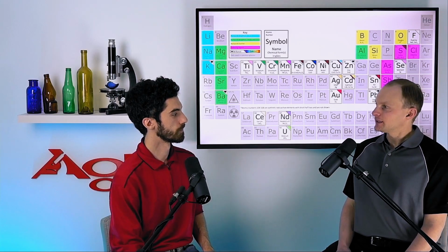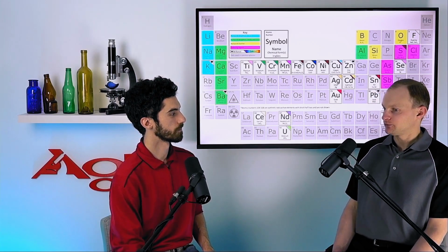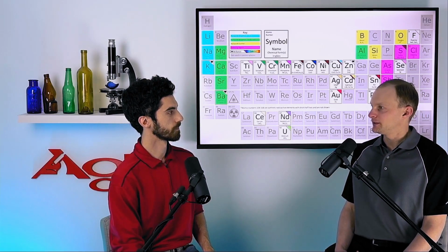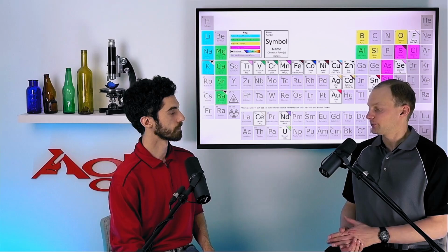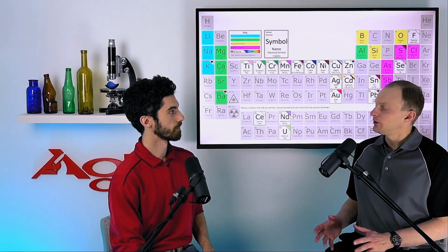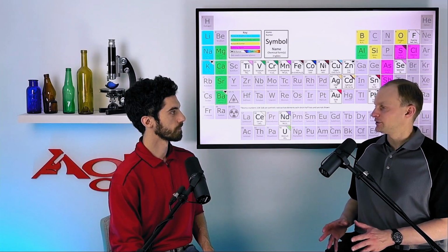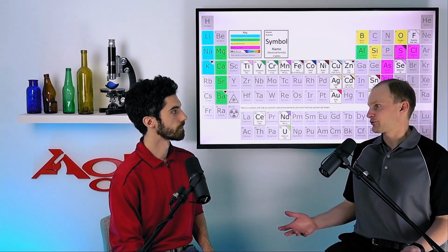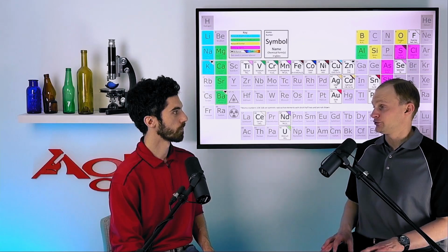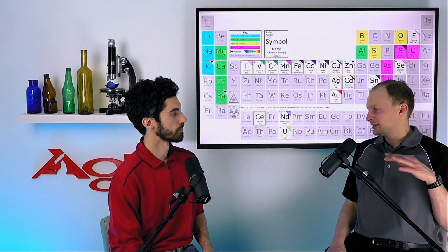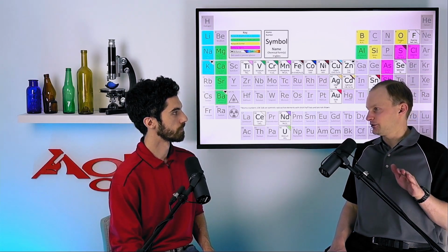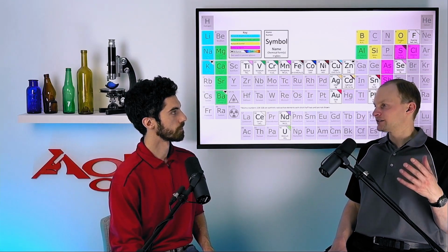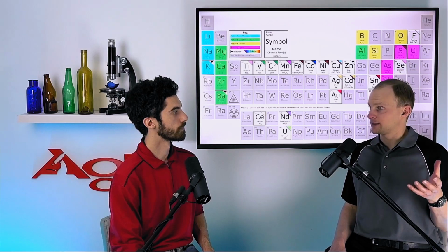It turns out that glass properties like fracture toughness and hardness don't really change much within a particular compositional range. So for soda lime silica glass, for all intents and purposes, the composition is not going to be the dominant factor in your fracture. That's almost certainly going to be negligible. So the little tiny tweaks that a glass company might make to their glass composition, changing something by 0.5% or 1%, really aren't going to affect the glass strength.